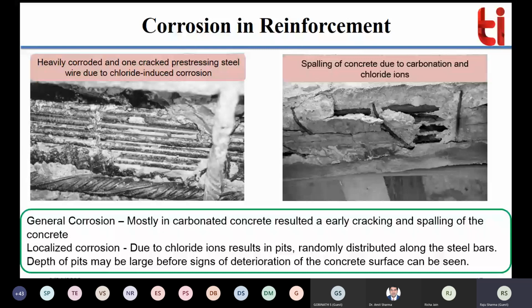In general, corrosion in carbonated concrete results in early cracking and spalling of the concrete, and it happens uniformly, okay? But localized corrosion happens due to chloride ions, meaning chloride ingress at some particular point, and that may affect the reinforcement from one particular location, right? And then it reduces the cross-sectional area of that particular reinforcement.